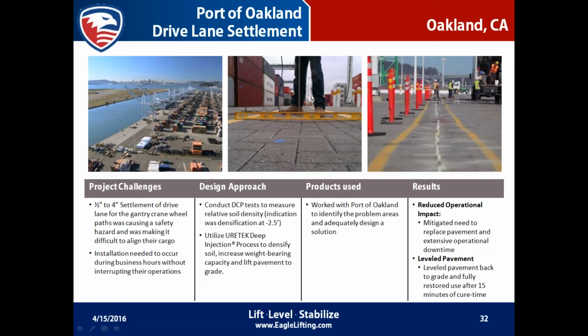Prior to any injections taking place, some DCP tests, or dynamic cone penetration tests, measured the relative soil density, which indicated that the subbase needed to be densified at least 2.5 foot depth. The URETEK process was then utilized to densify the soils and then lift the pavement to grade. The 2-part polymers injected through ½ inch tubes, once again at your 5-foot grid pattern, which you can actually see on the far right picture, directly underneath the wheel path for the gantry cranes. And the resulting mixture polymerized beneath the slab, creating minimal heat with optimum expansion. With the expansion, the material aggressively sought out the voids while densifying the surrounding soils and lifted the pavement back to its original elevation.